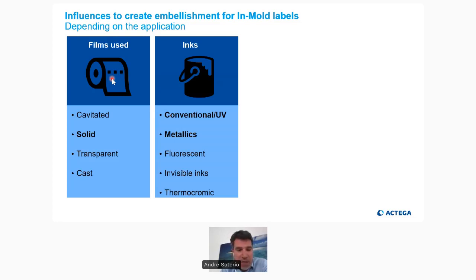Again, regulatory and low migration. Everybody talks a lot about UV coatings being low migration. There are different levels of product security. You have to be sure that when you are using UV coatings, you are not having any issues with migration onto the final product. And what we see lately is that there are many changes in UV regulations. Some photoinitiators are no longer allowed to be used in Europe. Now we have the issue with TMPTA, which also cannot be used in some of the coatings and inks. So there are a lot of changes, and you have to be sure that you comply with all the regulatory issues when using UV coatings.